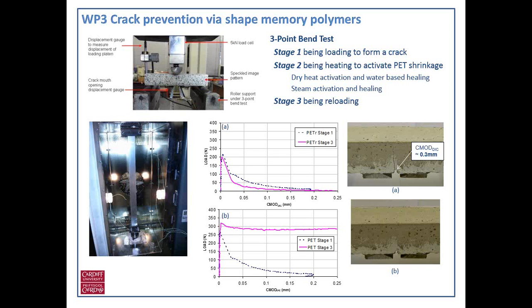So the idea is then to combine this to allow a system which actually restricts the crack growth to the sizes which the other two mechanisms from Bath and Cambridge can actually heal the cracks, thereby significantly increasing the durability of your concrete structure.